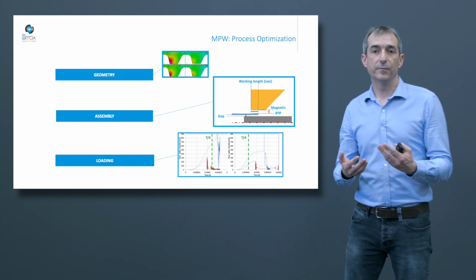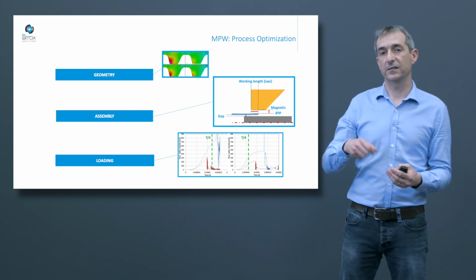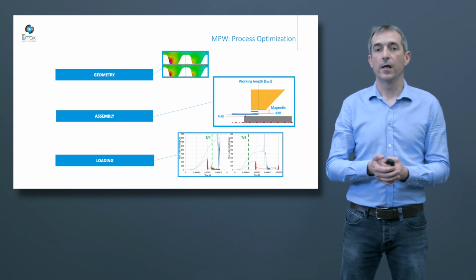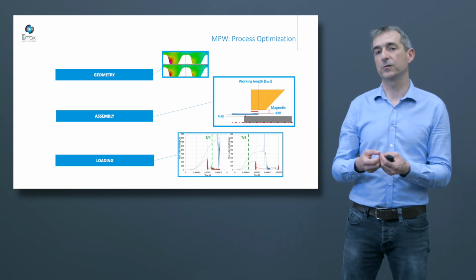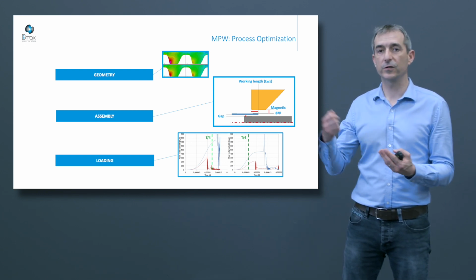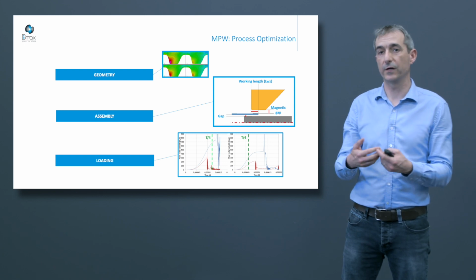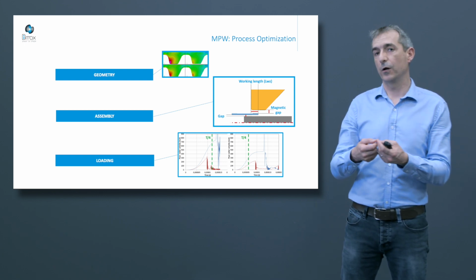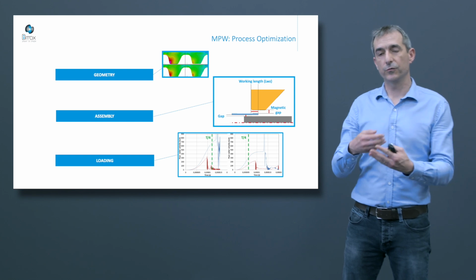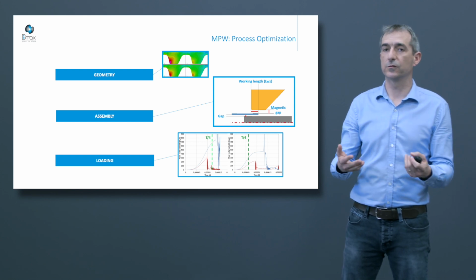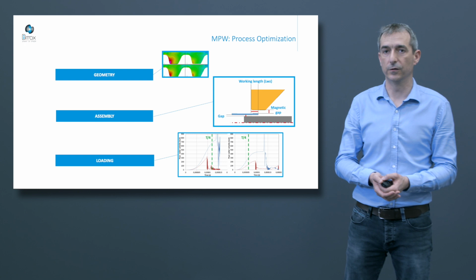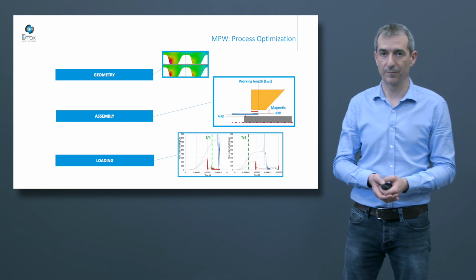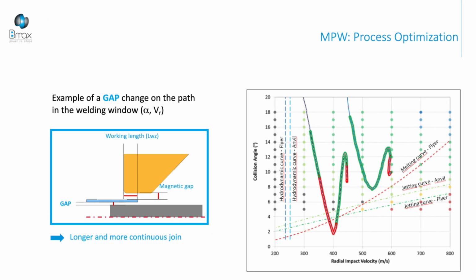At the end, we can optimize the loading in terms of maximum current, the energy level if you want, and the frequency. If the loading is too long, we have the maximum of force after the impact, so we don't create a very high impact velocity. If the loading is too fast, we don't push during the process, so it's not a good configuration to optimize the welding. So by simulation, we can change these parameters to define an optimized configuration and to enhance the welding.